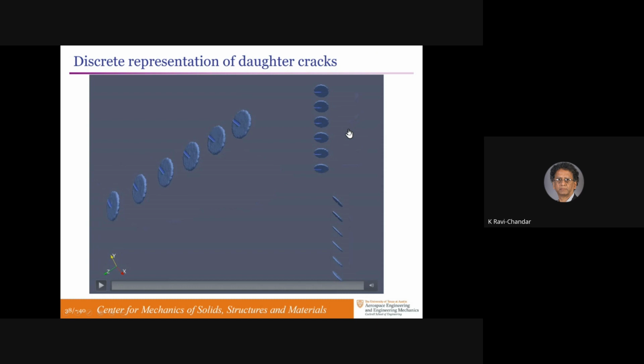So now let's do multiple cracks and see how they interact with each other. The parent crack is behind. You can see the intersection of the daughter crack with the parent crack. We put in a periodic array of daughter cracks to see how they would evolve and link up with each other. Now we don't have any more defects in here because the daughter cracks have already been spawned. We don't need defects.